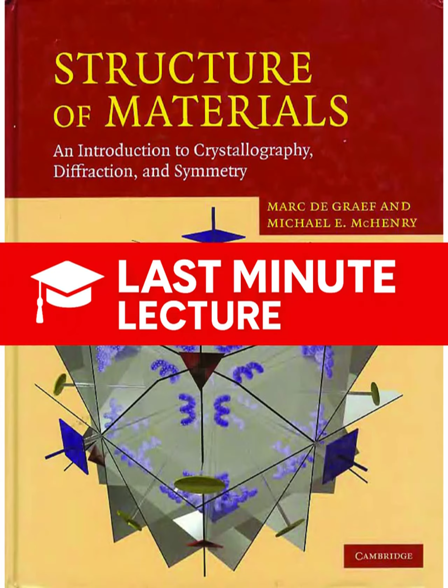Oh, wait, no, 111 is 3, odd. No, 110 would be odd. 110, right? Sum is 2, that's even. My mistake. Let's see. 100 is 1, odd, that's out. 110 sum is 2, even, that's in. 111 sum is 3, odd, that's out. 200 sum is 2, even, that's in. Okay, so you just sum the indices. If it's odd, the reflection is extinguished. That's the simple rule for body-centered.